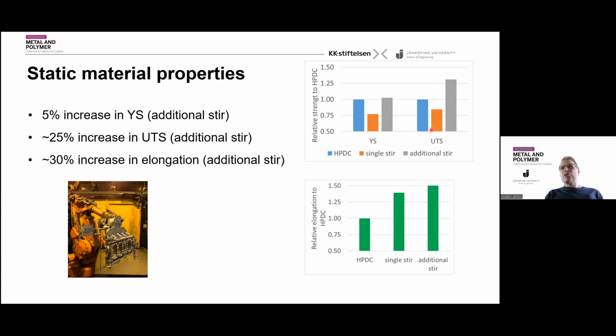And of course, as you know, materials harden during deformation, and of course, there must be some changes in elongation as well. Now, what you get, as you can see here, with the single stir, we had a slight reduction in yield strength. And that is also a consequence of how the material actually solidifies. And if you get something which is softer, you also have something which has a little bit of a better elongation. But what we managed to do with the additional stir was to recover that strength without loss of elongation. Actually, what we got was an improvement of elongation in this. So we could expand the elongation by 50% by doing the double stir as at the maximum, so to say.